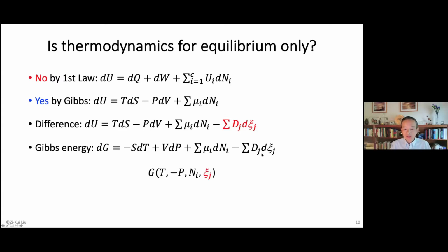Okay, the key thing would be you have to take the energy not only as a function of temperature, pressure, and the composition, or electric field, magnetic field. You have to also consider the internal degree of freedom. So that's internal variable is the key, right? So that means if we want to digitize thermodynamics, we have to take this term into consideration. That's exactly what Larry Kaufman did. He introduced a concept called lattice stability.